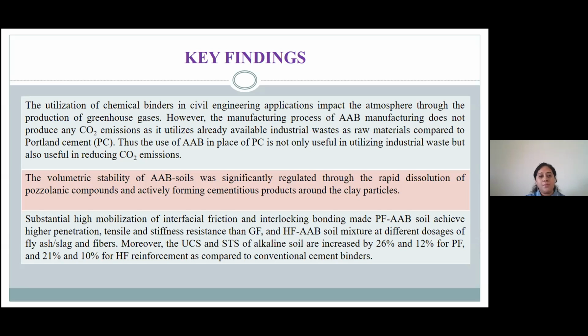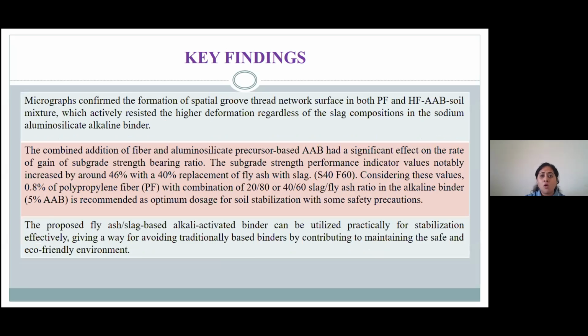In general, comparing natural and artificial fibers, polypropylene fiber gave better results compared to glass fiber, and hemp fibers gave better results compared to coir fibers. We also saw formation of some groove-like, network-like surfaces in all the fiber mixtures, along with the addition of fiber and the aluminosilicate precursor-based AAB.